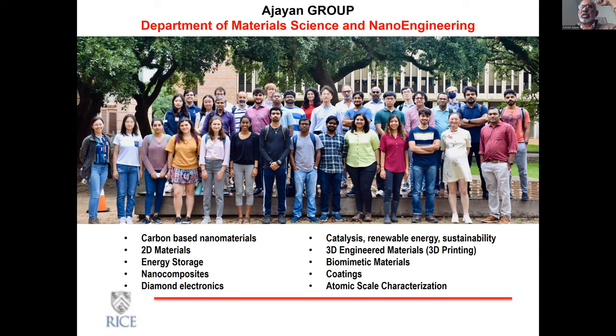So I think a lot of the work you now see in single atom catalysis and so on is related to this, identifying or playing around with the environment of individual elements that you substitutionally insert into graphene. So it's a loaded question. I mean, there can be very many answers depending on what you really are doing to the graphene. But broadly speaking, the reactivity certainly can be changed by chemistry. And as you said, if you do chemistry, you're changing the sp2 to sp3. So there's a change in bonding, change in behavior, the band gap. So you're not really talking about the same material for sure.